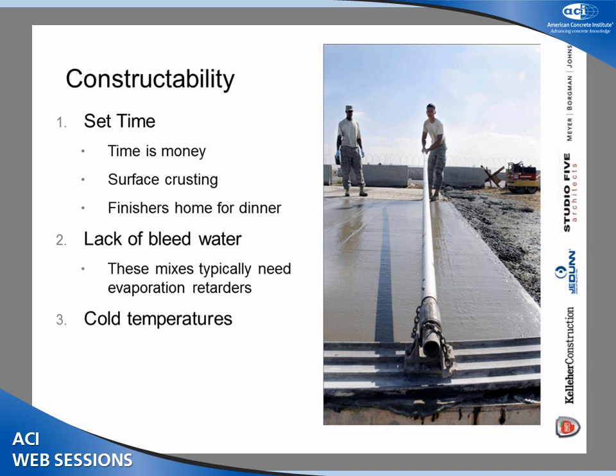And we're working at it all the time, and I'm definitely interested in exploring some of these approaches with internal curing and getting more ground limestone, finely ground limestone in the mix. It sounds more expensive, and we'll have to look at that carefully. I was surprised to hear just recently that every bag of Portland cement you buy these days has 3 to 5% ground limestone in it already. That was news to me. So our mixes here, unbeknownst to me, were really quaternary blends, because they had slag, fly ash, Portland, and limestone in them, and they did quite well.